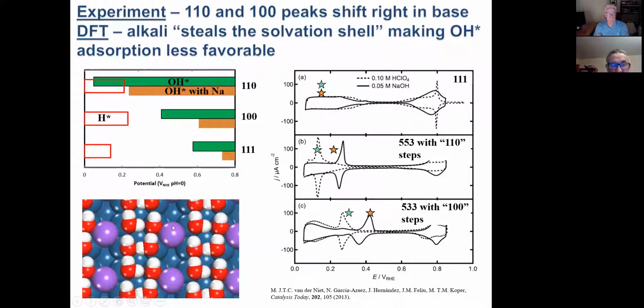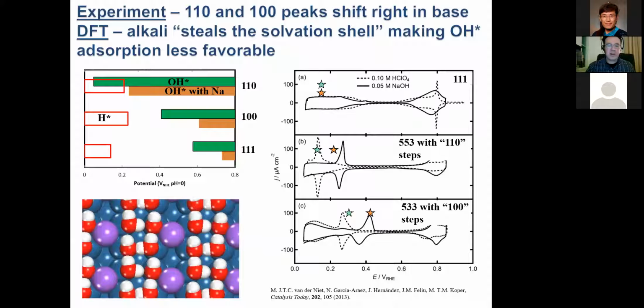And now you, of course, might question, if you do DFT calculations, that that's a result you'd get based on some arbitrary place I put the sodium, and the real system would have a wide distribution of structures. We spend a lot of time looking at different structures, different arrangements to make sure this result is very robust. Qualitatively, the sodium steals the solvation and disrupts the ability of water to interact with hydroxide.